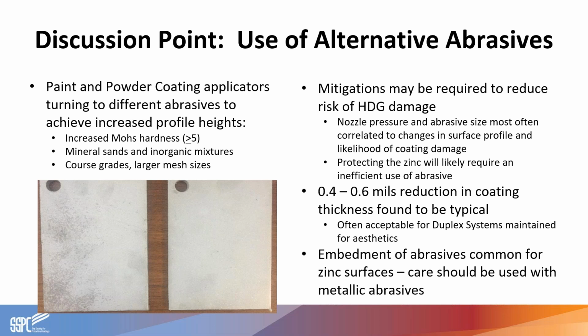So to kind of wrap our head around this issue, the AGA completed a study last year that evaluated different types of mineral sands and inorganic abrasives. And what we found was that the nozzle pressure and abrasive size were two of the most influential factors related to changes in the surface profile properties and the likelihood of coating damage. If you're looking to achieve more in the range of a 2 to 4 mil profile height with hot dip galvanizing using these types of materials, it's doable. But you will need to dial back pressures and standoff distances when blasting.